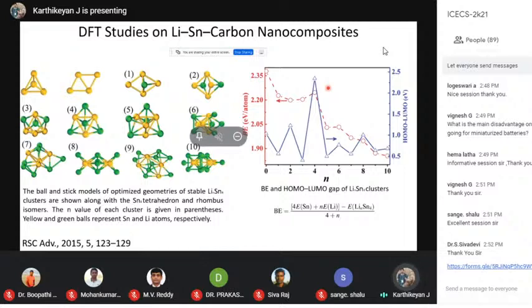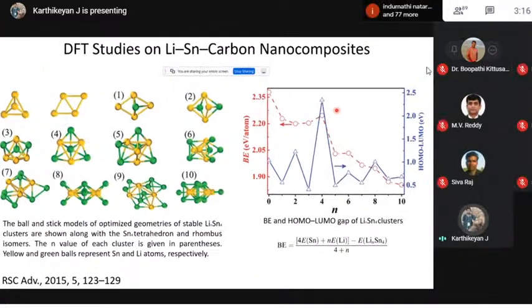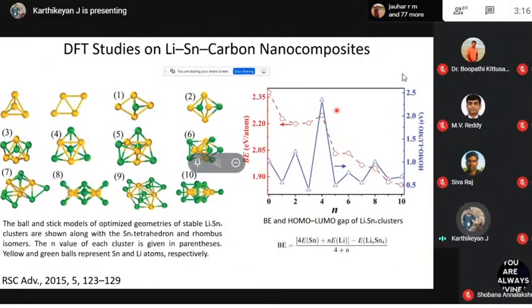So what's the reason? What is happening in this cluster system? When you add lithium atoms, the binding energy between tin and lithium keeps decreasing slightly, and suddenly when n equals 4, it forms a peak. This form of the cluster is called a Zintl phase cluster. That was the main reason we chose Sn4: the Zintl phase formation, which also happens in bulk form, can be mimicked by a small cluster. In bulk form too, tin-lithium alloys form Zintl phases, and this can be mimicked using a very small cluster system.